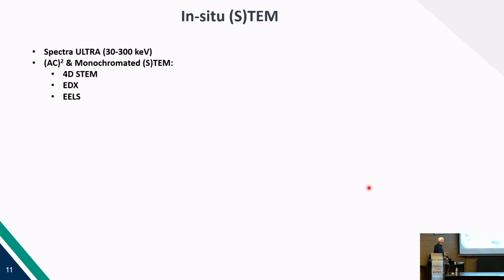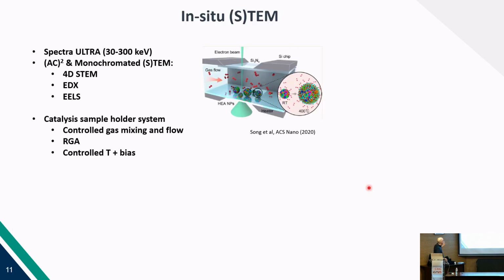So what you need is really a lot of computers behind in order to do something with all this data. And this is the microscope, for which the public tender is over now. So we could sign the contract before Christmas. And now we know that we need to wait 1 year in order to get the machine. But the microscope is the most modern microscope that Thermo Fisher has at the moment. It's a Spectra Ultra. It can work from nearly 30 kilo electron volts to 300. So you can work at the energy of an SEM to the really high energy, 300 kilovolts. It's double corrected, monochromated, with all the different techniques you want.